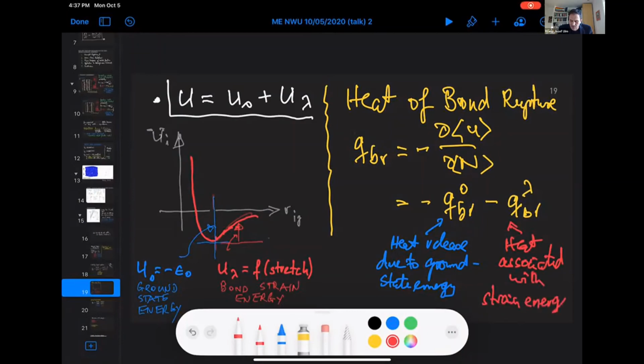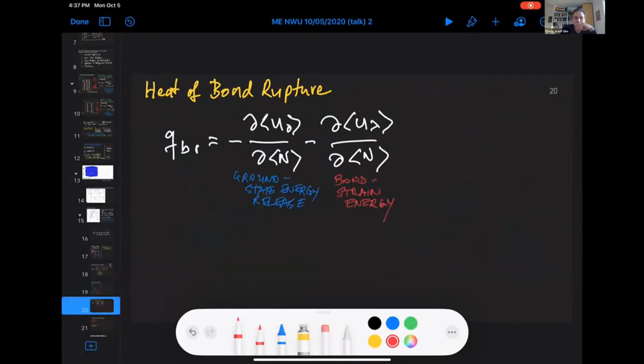And why does that matter? Well, bear with me. Now let's look at these two terms. We have the ground state energy on the one side, and on the other side, the bond strain energy release. Now think about the equivalent from fracture mechanics. As long as the heat of the ground state energy which you release is greater than what is required from the bond strain energy, so as long as this quantity is greater than zero, the process is stable.